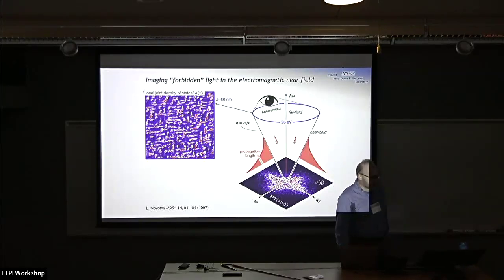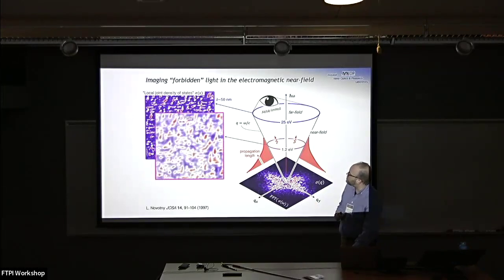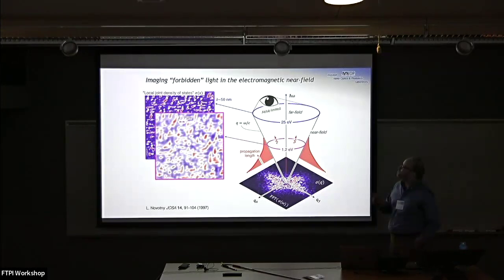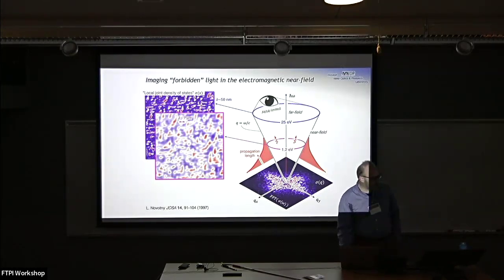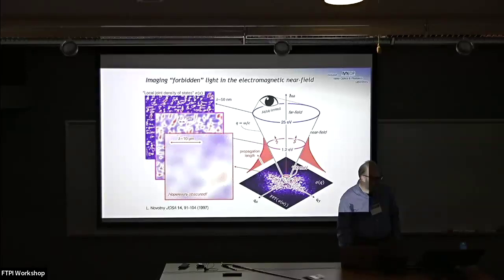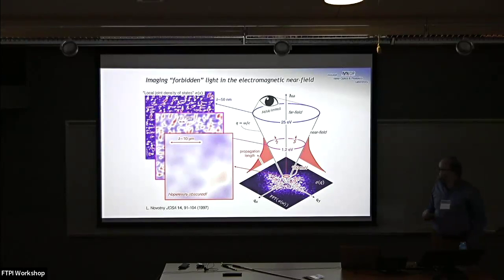And if we do an Abbe limited experiment at 25 electron volts, which is not going to show you the distinction between insulator and metal, but if it were, we would obtain a lovely image. Unfortunately, we don't have contrast. There's no difference between the two materials at 25 eV. So what if we go down to ultraviolet? Again, the conductivity is not dissimilar between the two there, and it would be blurred. And here is where I want to be. Low energy photons result in a low energy response, but the phases are hopelessly obscured.